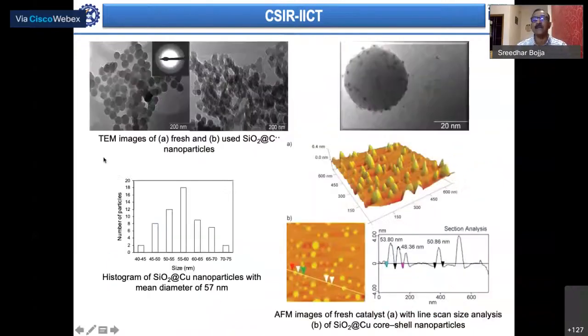We try to characterize it by various techniques like TEM, AFM, and others. What is very important in this characterization is that when you analyze by two or more techniques, the results should correlate, and the size should be uniform. For example, by TEM analysis it is about 55 to 60 nanometers, and by atomic force microscope, the sizes are between 50 to 55 nanometers, with similar shapes.